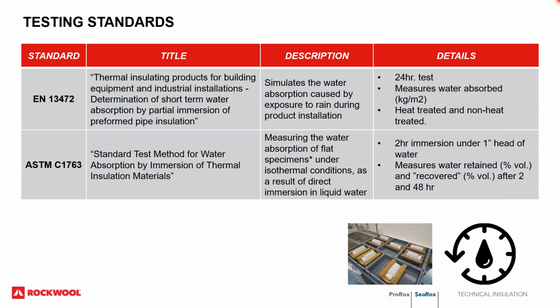The EN 13472 test is a partial submersion test. So in the lower left-hand corner of this slide, you'll see a pipe section sitting in a bath of distilled water, and it's weighted down with a bottle at the core there. So this is partially submerging the insulation in water. The ASTM test is similar, but it's actually designed for flat specimens. So that's fundamentally the difference between the two tests. The EN standard is specifically designed for pipe-shaped insulation, whereas the ASTM standard is designed for flat insulation. And in the ASTM standard, we submerged it to a depth of about 1 inch for 2 hours, and we measured the water absorption at a recovery time of 2 hours and 48 hours after wetting. So we wanted to see how fast it took the insulation to recover.